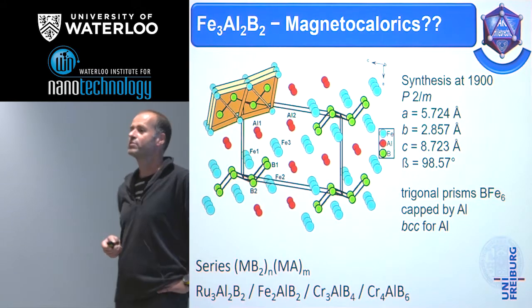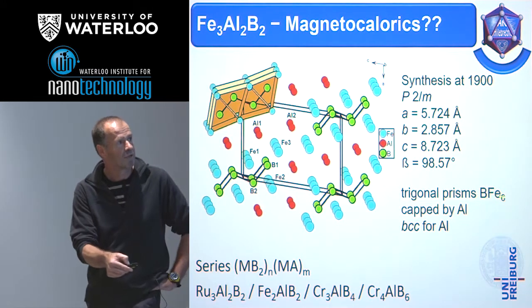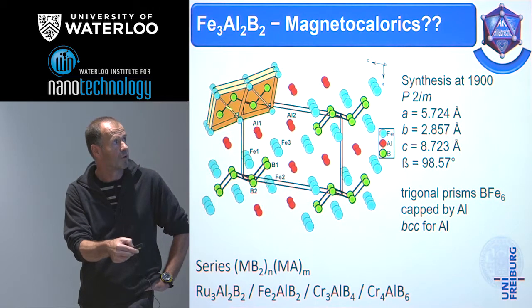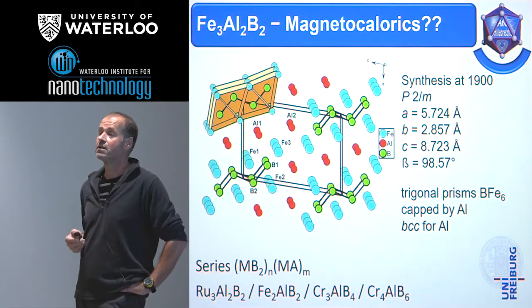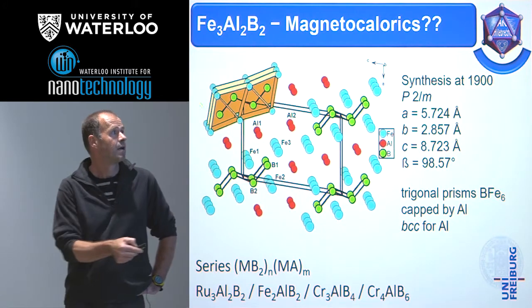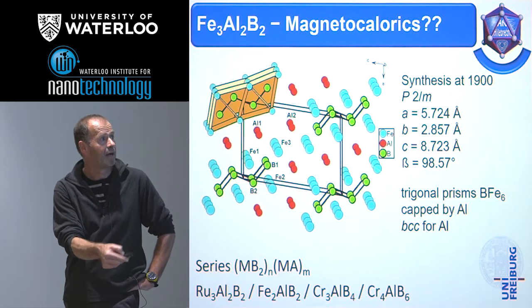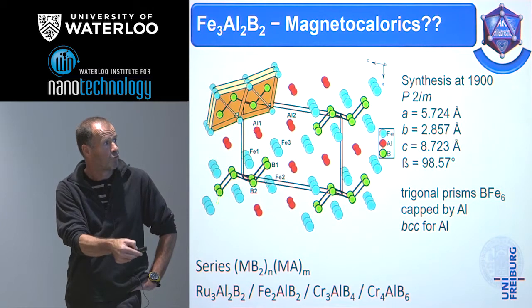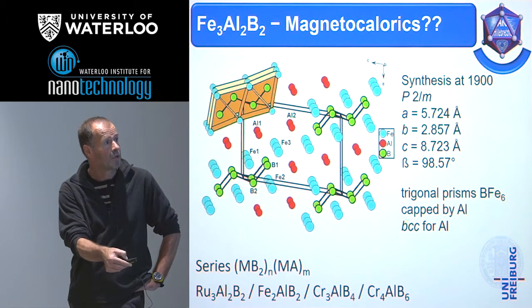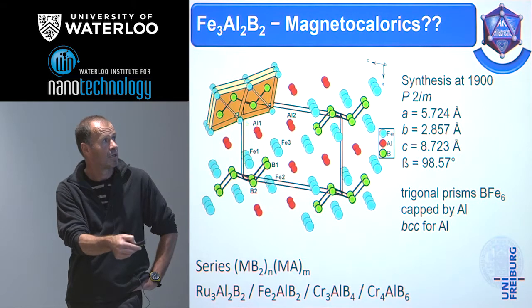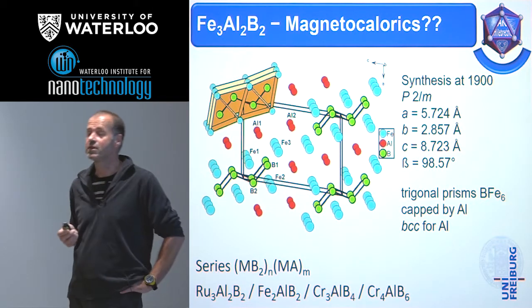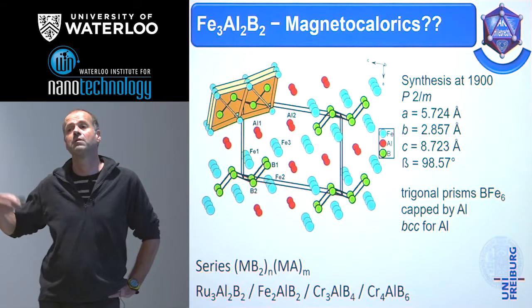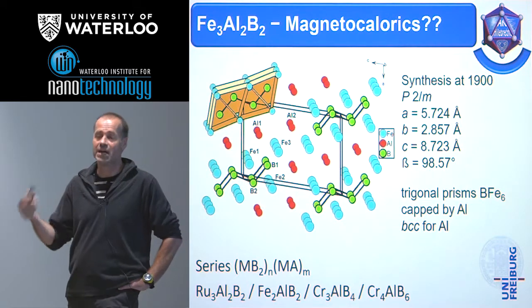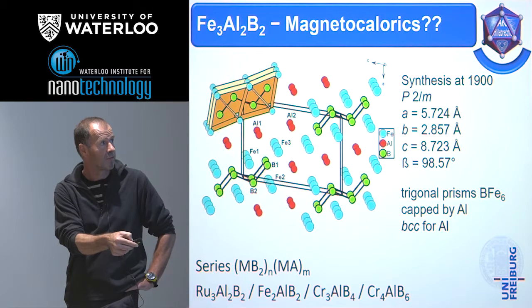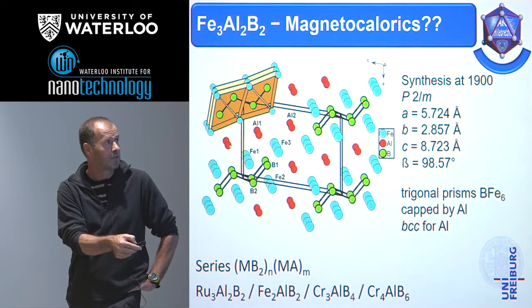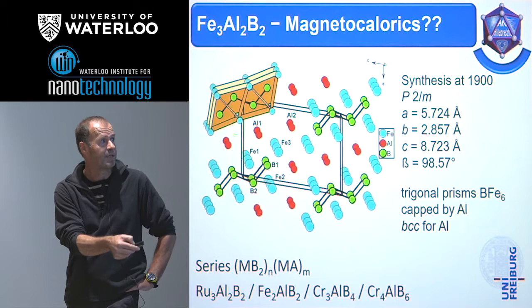As we know it from all the transition metal borides, there are trigonal prisms around the boron with a transition metal, and as always, the sides are capped by other boron atoms to form boron-boron bonds, or by a second metal. And usually there is a high preference of the transition metal, compared to metals like aluminum, for the direct interaction between boron and the metal, and the aluminum metal prefers the capping sites.